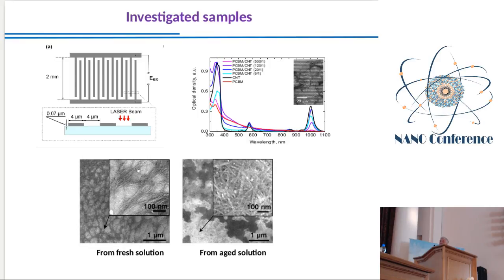We use samples, as I told, of mixtures of carbon nanotubes and PCBM molecules. Here you see micrograph images of these samples. We prepared these samples from fresh solution and from aged solution, and these samples showed quite different electronic properties. When we have fresh solutions, we have long, spaghetti-type carbon nanotubes. But when solutions were aged for several months, they formed some aggregates, and here these carbon nanotubes are just mixed between one another, so just a different morphology of our samples.